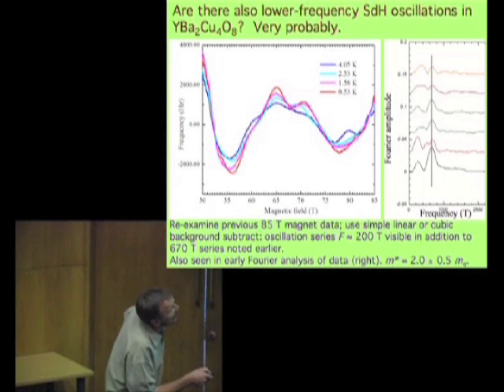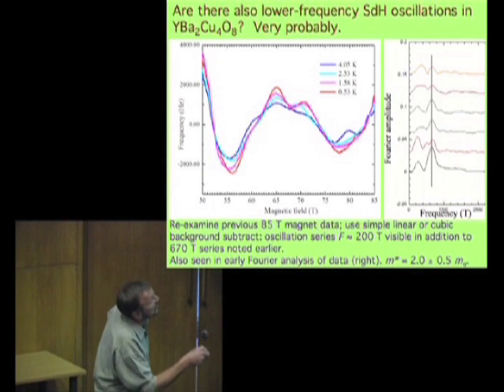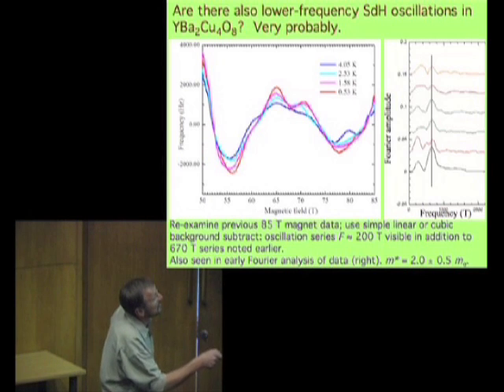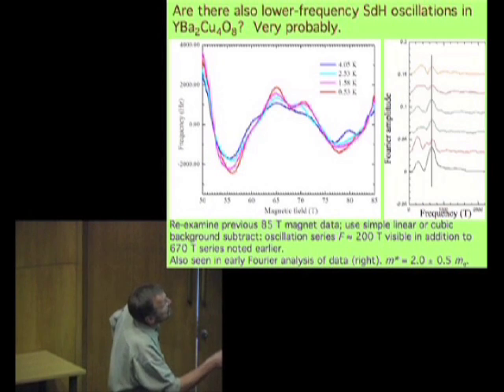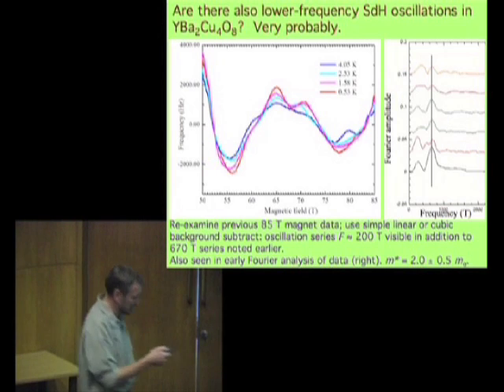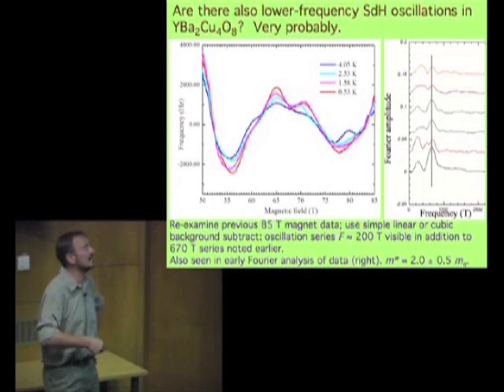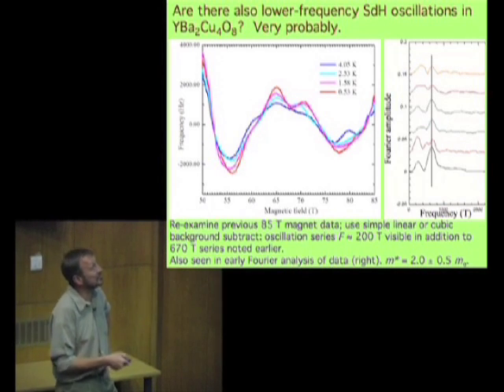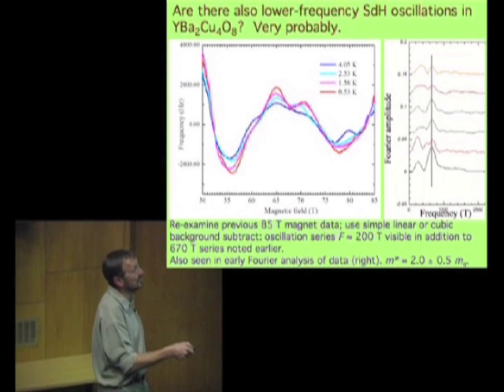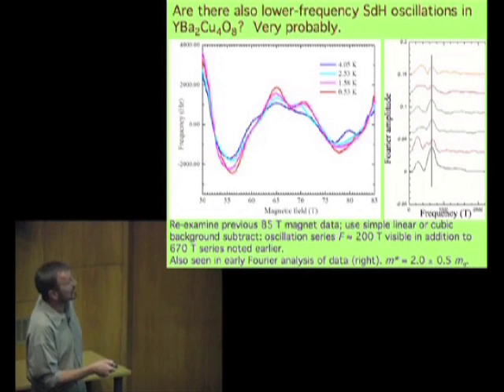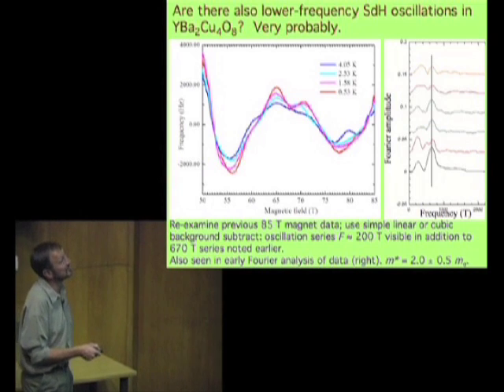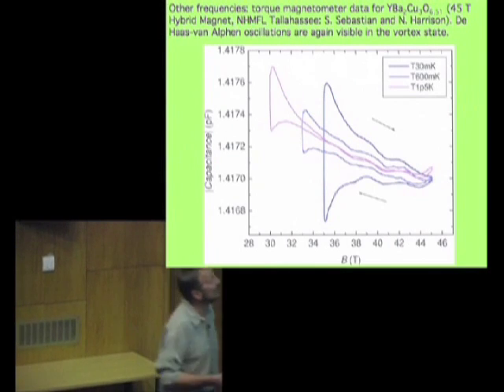And indeed, in the very first Fourier transforms, this is something that was scanned out of my logbook and labels typed on later, this lower frequency is also present. So it looks as though you have a low frequency of about 200 Tesla and a higher frequency which is between 500 and 700 Tesla in the various dopings we've seen. Finally,